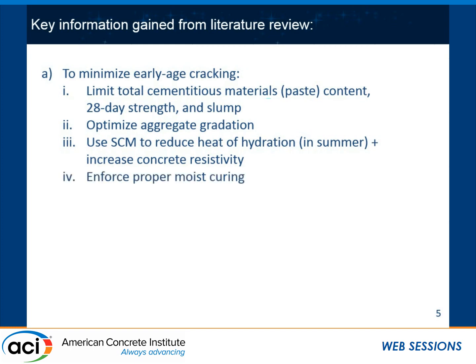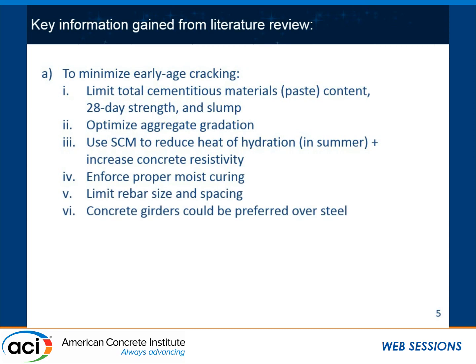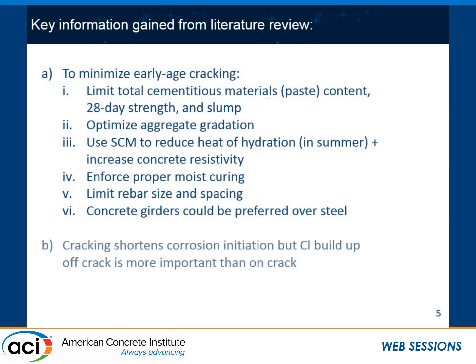Enforce proper moist curing, so that helps reduce the overall shrinkage and also delays when the shrinkage happens. Limiting rebar size and spacing, again, helps in controlling the cracks. And there was some mention that concrete girders may be preferred over steel girders, and I'll talk about that more in our data. Also, the literature suggests that cracking shortens the corrosion initiation.